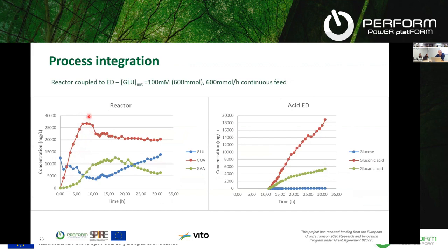concentrations are increasing, and after some time we switch on the electrodialysis, and you can see that it automatically has an effect on the gluconic acid concentration. Meanwhile, of course, this is a continuous fed experiment, so there will be some stabilization of the gluconic acid in the reaction mixture. So this is actually the analyte concentration. On the other hand, if we look at the acidic compartment of the electrodialysis, we see definitely no glucose entering there. So we have a perfect separation of glucose and the acids, and you can see that the concentration of acids is increasing in the acid compartment of the electrodialysis.